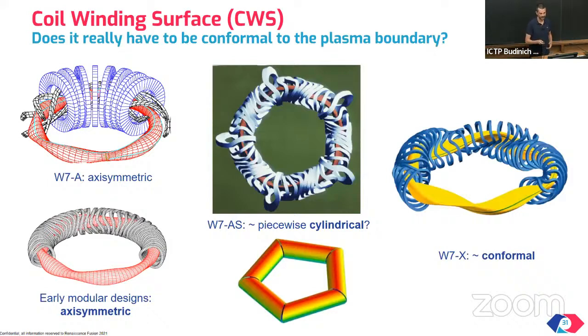So historically, the coil winding surface, so the surface on which these coils have been designed, has become more and more complicated, as you see in this illustration. The point is that we want to accurately generate the magnetic field that confines the plasma in yellow. And if you choose a conformal coil winding surface, conformal in the sense of parallel to the plasma boundary, and you stay close enough to the plasma, this is typically considered to be good. You don't want to be away from the plasma because high-order multipoles decay more rapidly. And for the same amount of plasma shaping, you need more coil shaping. This effort of staying close to the plasma, I think we have overdone it.